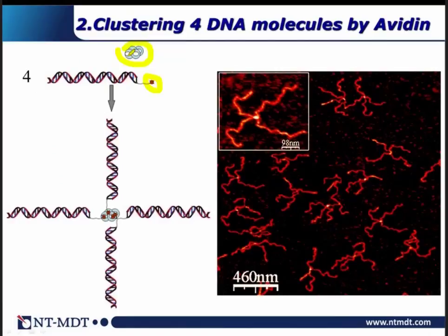We need to saturate those binding sites. And what's happened? Biotin interacts with those sites, and you produce a complex where 4 double-stranded poly-G poly-C molecules clustered are interacting with this Avidin system. Now we can see proof coming from AFM.